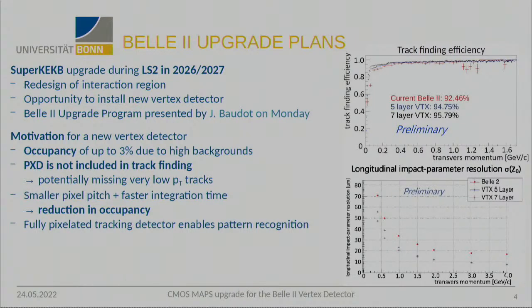The motivation for a new vertex detector is that for the innermost PXD layer, we expect occupancies of up to 3% due to beam-induced backgrounds. The PXD is not included in track finding, which you can see here, where I show in red the current Belle II detector that achieves 92.5% track finding efficiency. But especially in the low PT region, where the particles do not really enter our main tracking detector, our drift chamber, having 2 additional layers for track finding really helps improve the track finding efficiency.